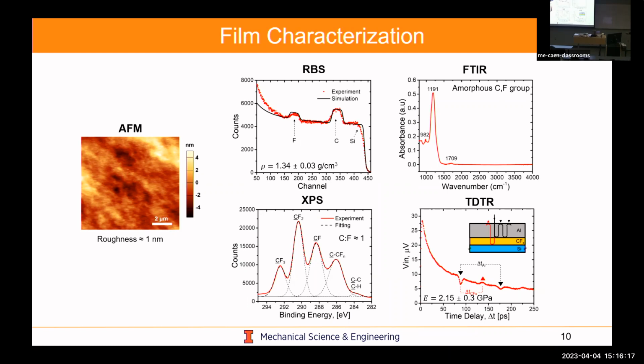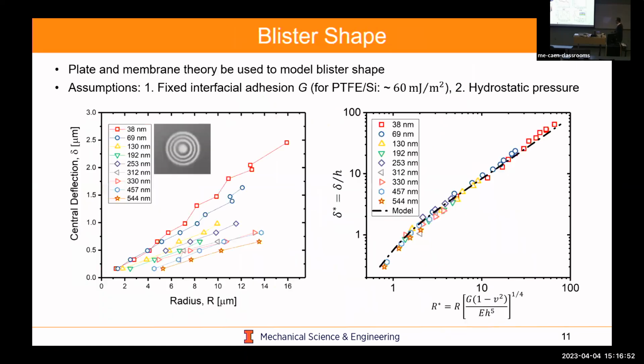Very low roughness, silicon coated, C4 FX chemistries, right? So very smooth. We do Rutherford backscattering to measure things like density of our polymer films, FTIR to look at amorphous CF groups, XPS to look at the actual structure of the polymers we're depositing, and then TDTR to actually measure thickness, but also you could actually use time-domain thermoreflectance to measure things like Young's modulus of your polymers. And so by combining all of these, we could then have a very well-characterized system to really understand how these blisters grow and what's actually affecting their formation.